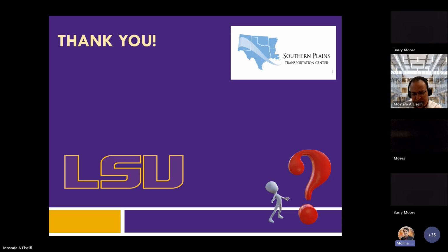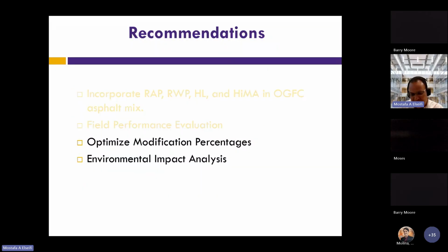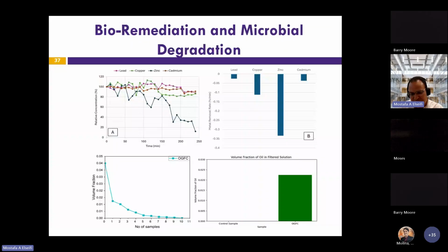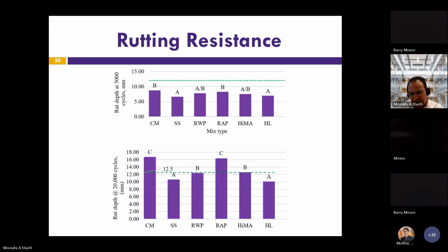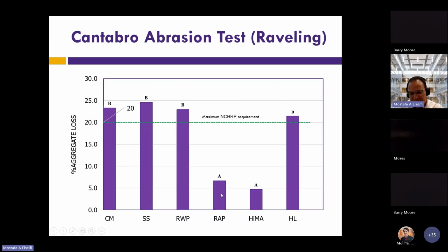All right. And next question is, are all 4 of the tests of equal importance in performance? And this is a good point. So again, I would think that raveling is probably the most important one. And if I go back to this slide, if we see the raveling here, you can see that RAP and HiMA had an exceptional performance compared to the other mixes. So this is probably the most important test, followed by the IDEAL-CT. And that's, again, because the cracking susceptibility of the mix is very high.